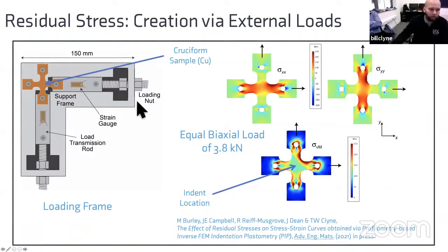So you can see that we've got a cruciform shaped sample, and these 2 points here and here are fixed. And in these ones here, we apply a load through the loading nut and measure effectively the applied load through this strain gauge here. So in 2 different directions, we can pull on these loading nuts, generating a stress in the material, and we hold that constant as we perform the indentation.